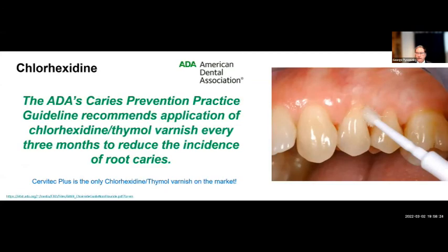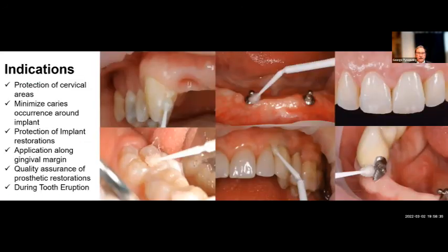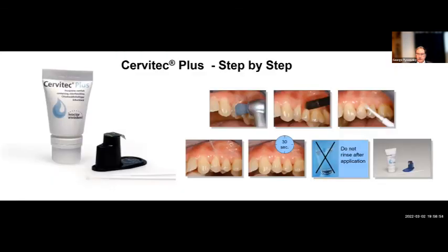The recommendation is to use this on a routine basis, following the ADA's caries prevention practice guidelines. You paint it onto the margins of the restoration, let it polymerize, and it maintains itself, releasing the chemicals to provide the benefit. It can be used on implants, on restorations, a variety of different surfaces, as an antimicrobial and a periodontal enhancement supplement. So this is the step-by-step: we clean, we dry, we apply, let it air dry, and then let the material provide the benefit that it can.